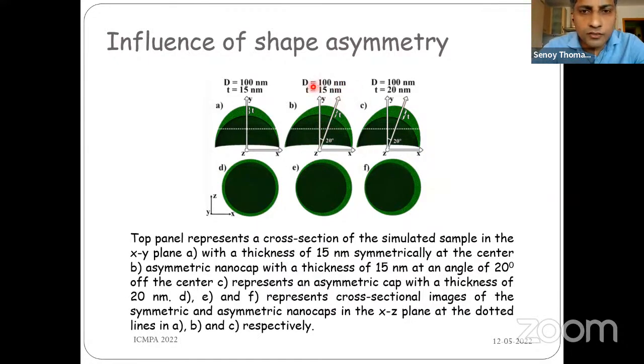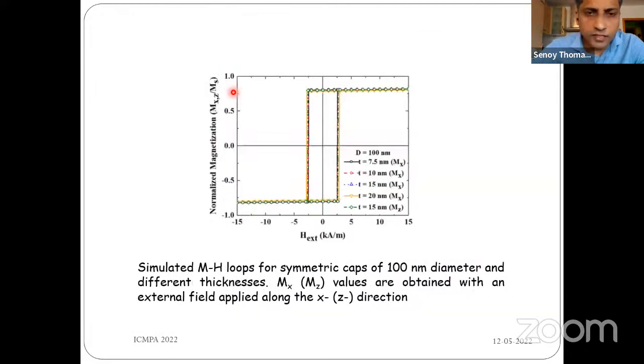So we did simulations for different thicknesses, and the results are summarized here. Here is the simulated MH curve for symmetric caps having different thicknesses, by applying the field along the X as well as the Z direction. What one could see here is that the loops are overlapping for the measurements with the field applied in different directions.